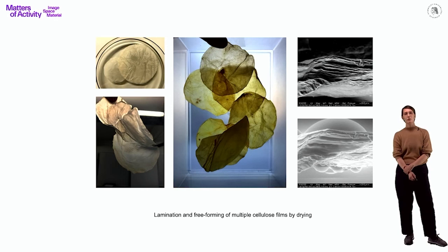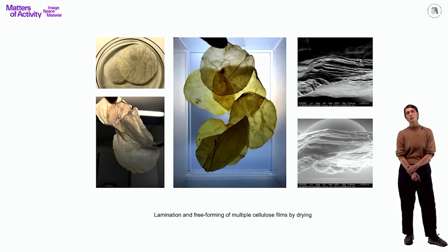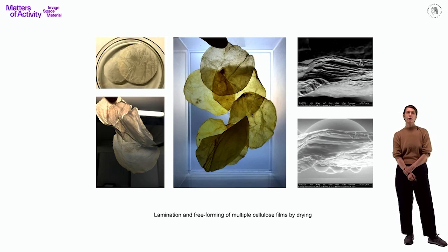The drying process not only causes shrinking, but in some cases also strong adhesion. By overlapping individual sheets of cellulose and connecting them by magnets during the drying process, we were able to create larger formations without an additional connecting structure. Kurkuma was used for coloring with an intention to explore natural substances that could prevent biofilm from molding.